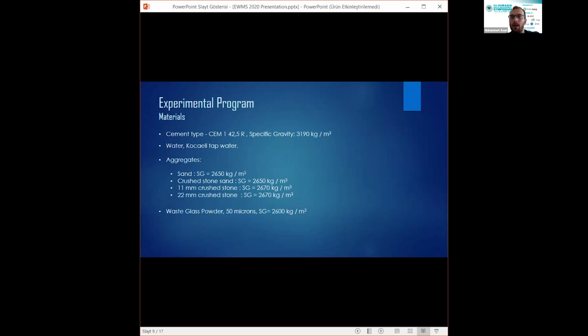And we use 4 types of aggregates: natural sand, crushed stone sand, and crushed stones, one of which has 11 millimeter maximum grain size, and the other has 22 millimeter maximum aggregate size. The specific gravity of fine aggregates is 2.65 tons per cubic meter, and for coarse aggregates, 2.67 tons per cubic meter.